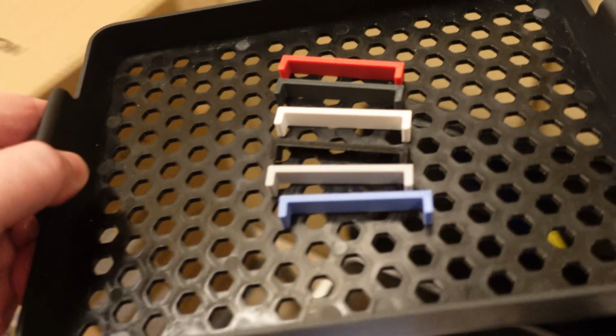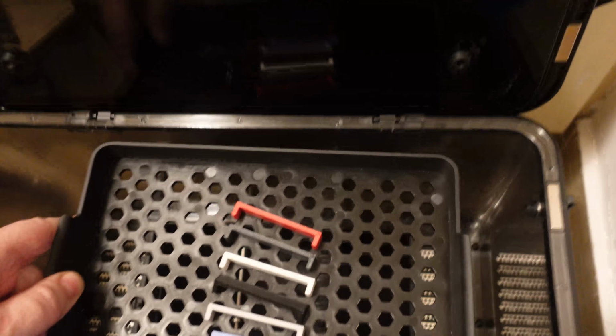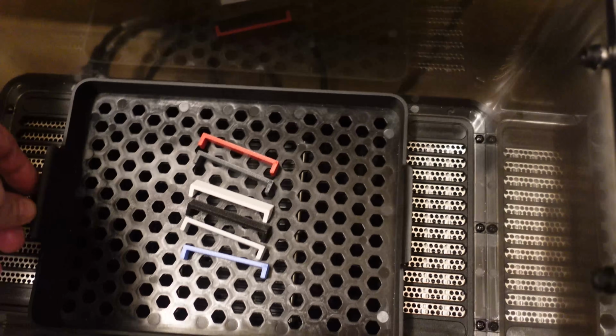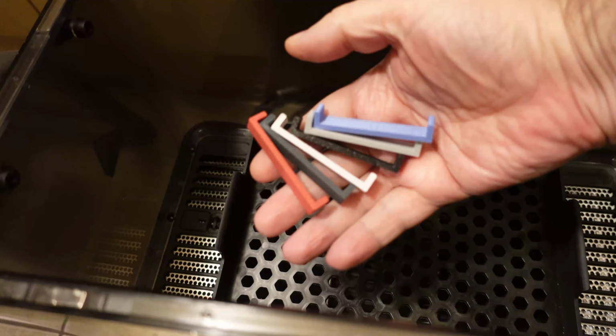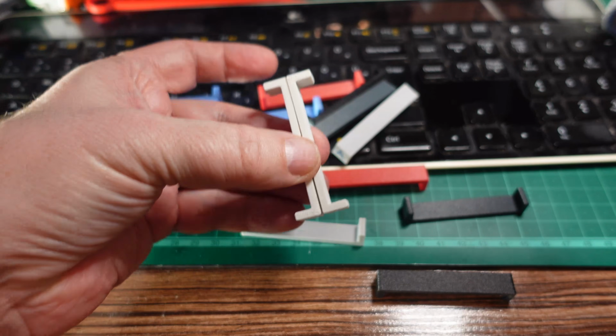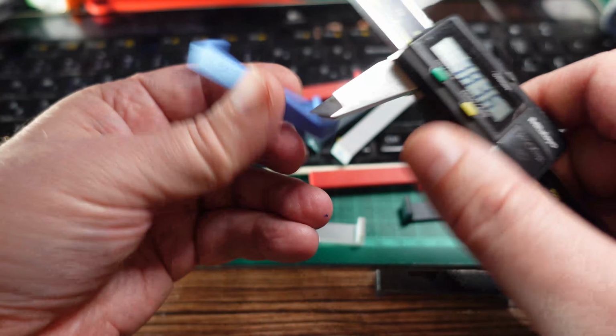And now annealing of these test objects for the temperature test. They will be annealed at 115 degrees Celsius in a Sunlu E2 filament dryer, which is a prototype, and by error it can reach this higher temperature. And after 2 hours I let it cool down together with the dryer. Visually there is no deformation on these test objects.